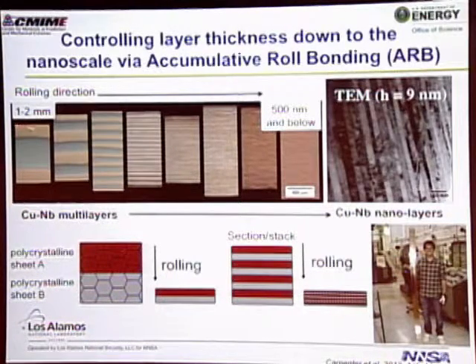So if we can imagine two sheets of material, copper and niobium in this case, we can actually look down at the schematic here. We take copper and niobium, we roll them through a rolling mill. You'll see a picture of one of those in just a moment, and they'll bond together and make a very long sheet, like you can see our student Tom Nozolek holding right here. Then you cut that up, stack it again, and roll it again. And you do this over and over and over again, which is why it's called cumulative roll bonding. And what happens is you start with a material that looks like this, with layer thicknesses of millimeters, and you can drop all the way down to 9 nanometers in layer thickness.